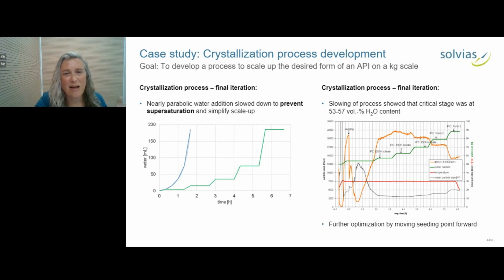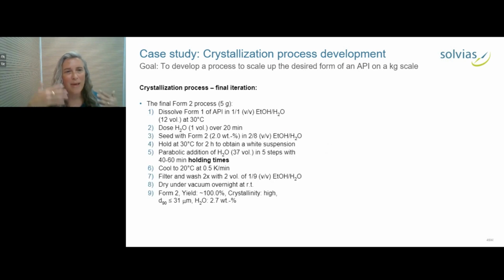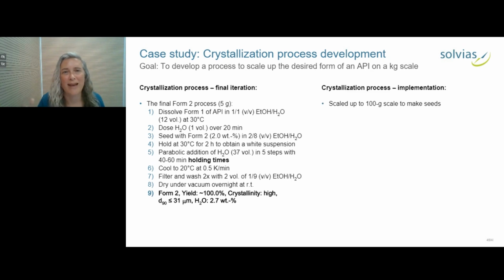And then there was additional optimization with the seeding point. We played around with temperature cycling, but it didn't help. In the end, we got this final process listed here, where we had these holding times. And what we got was form 2 with basically a quantitative yield, high crystallinity, small particle size, the amount of water we would expect for a channel hydrate, and no residual organic solvent.